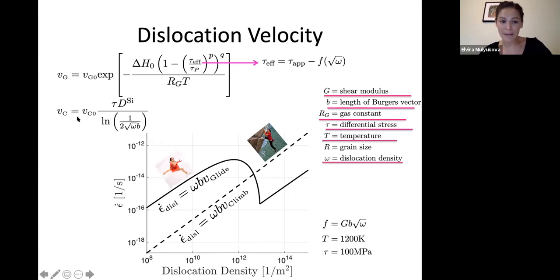And then climb, like I mentioned earlier, is a diffusive process. So it requires diffusion across the grain. And it is typically limited by the slowest diffusing species, which for olivine, one of the main components of the upper mantle and lithosphere, is silicon. So that is one of the reasons climb is slower.